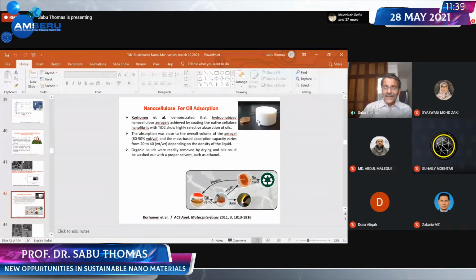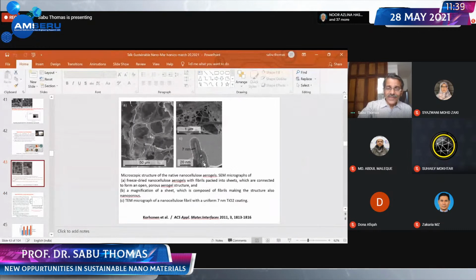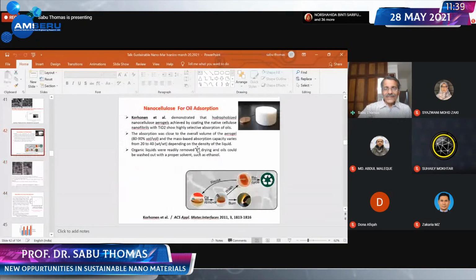And the Finnish group, you know what they did? They did something interesting. They made the surface of this aerogel hydrophobic. How did they do that? They did a coating of TiO2, titanium dioxide, on the surface of the aerogel. A 7 nanometer coating on the surface. You know, the diameter of the nanofiber is 25 to 30 nanometer. So they gave a coating of 7 nanometer on the surface. Once you do such a coating, look at this. The surface becomes hydrophobic. So this surface can absorb all the oil. The red one is oil. This is seawater. It can take all the oil. It cannot take water because it's hydrophobic.